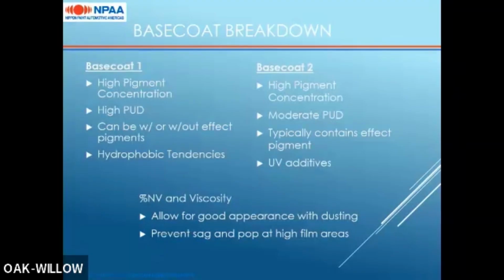Then base 2 is designed for high pigment concentration. It has also a higher PUD level than a standard coating, but lower than the base 1. Typically contains effect pigments and UV additives. Then both of them are designed with the NV and viscosity or rheology optimized to allow for good appearance, particularly in areas where there's overdusting, so along interiors, crossover sections, as well as to prevent sag and pop at high film build areas.